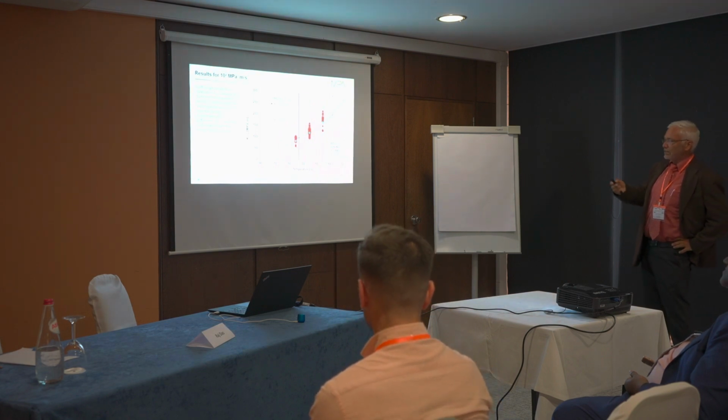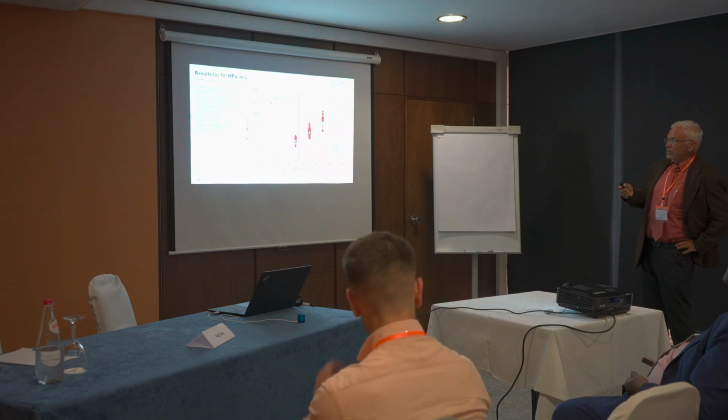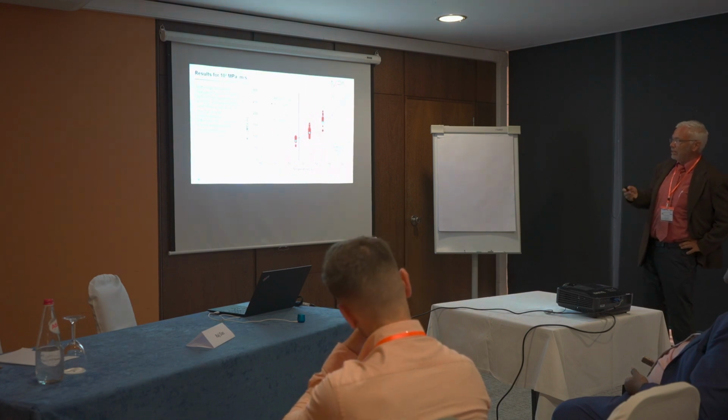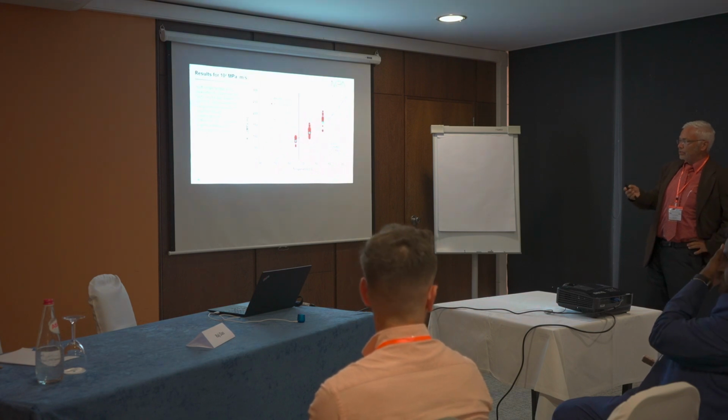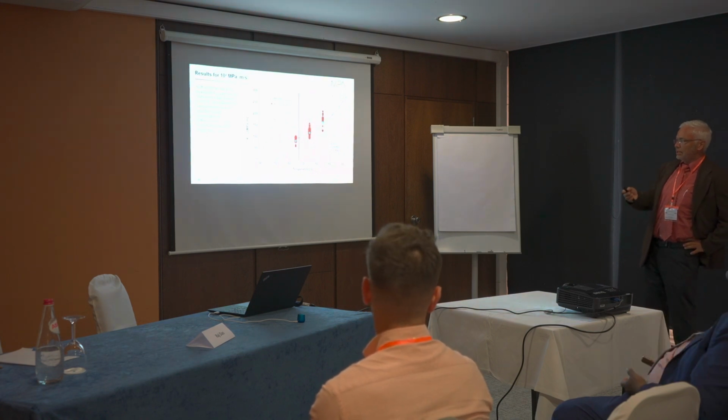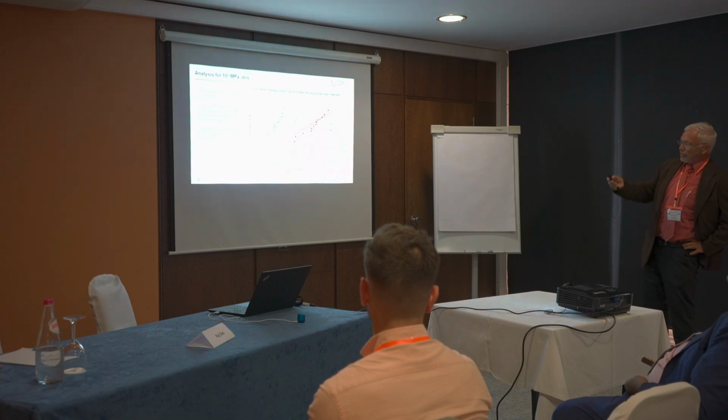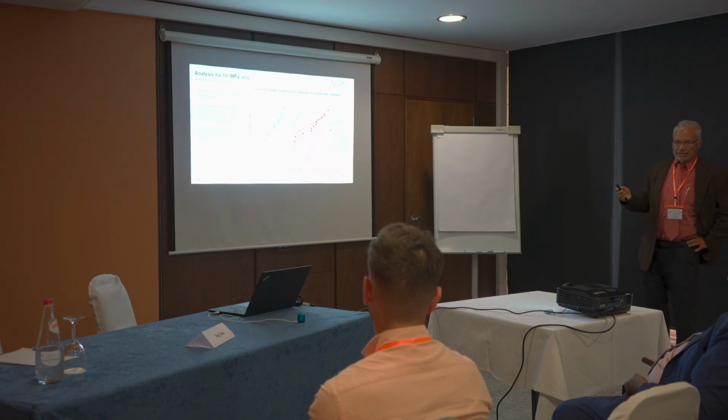And this is the same for 10 to the 4th. Still you can see an influence for higher test temperatures, a shift of also 10 degrees Celsius for the result. And here we have the most tests at -20 degrees, and also there the fit doesn't match the solid line, which is from the standard distribution.